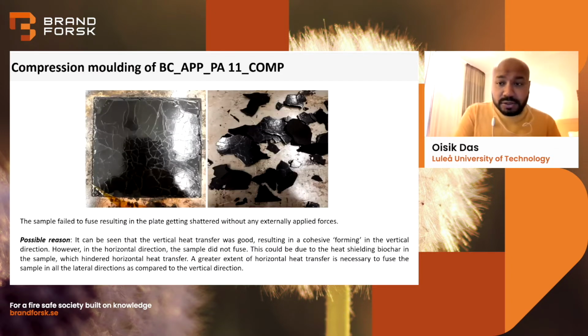So I will talk about two issues that we had. I wouldn't call them issues, but two results, in fact. So when we tried to compression mold the APP doped biochar in polyamide, the samples all the time shattered, as we can see, shattered like glass. And the reason we speculate is that because of the heat shielding biochar, the molten polymer was not able to form in a lateral direction, although it was able to form in the vertical direction. In the lateral direction, it had a lot of biochar, so it was not able to flow throughout the length and breadth of the sample to form. And that's why, after processing, it shattered.